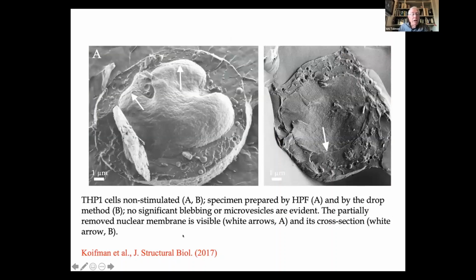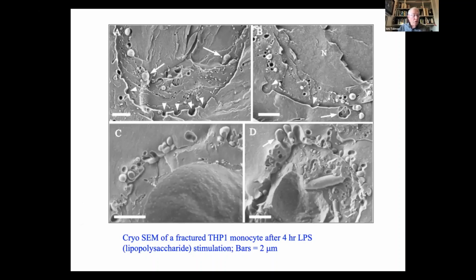Here we have a very nice monocyte, and you can see here the entire monocyte. This is the nucleus, and then here you can see the entire cell. In this case, the cell itself was fractured, but the fracture surface went over the nucleus, so the nucleus itself was not fractured. In some areas here, you can even see the nuclear membrane with nuclear pores. In this case, the fracture went through the nucleus, and you can see very well the fractured nucleus and the fractured cell.